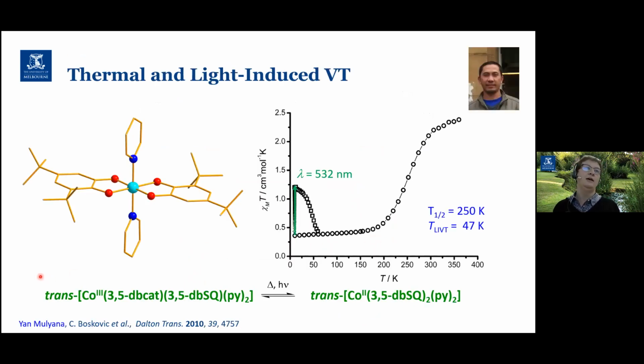This is actually the first system we looked at, and this is my very first PhD student, Yan Mulyana. A really simple mononuclear complex: cobalt coordinated to 2 trans-pyridyl ligands and 2 3,5-ditertbutyl dioxolenes. At low temperature this is cobalt-3. One of those dioxolenes is in the catechol form, the other one's in the semiquinone form. We can heat that system up and monitor it by magnetic susceptibility or other techniques as well. You can see a really nice transition, half temperature of about 250 Kelvin. The electron is transferred from the catechol to the cobalt-3, and you end up with cobalt-2 and 2 semiquinone ligands.